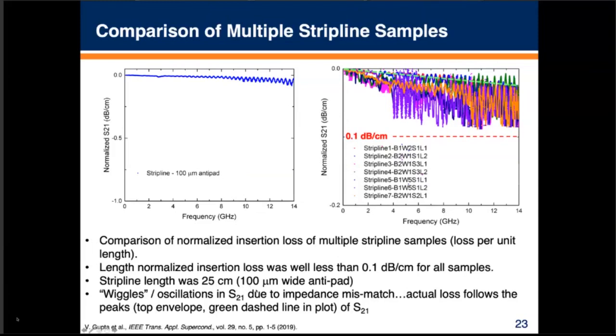And I mentioned here that we have a 100 micron wide anti-pad underneath that just to help with some impedance mismatch. And that's actually where these small wiggles come from. With such low loss, it doesn't take much of an impedance mismatch to cause these little oscillations. At each end of the line, you basically build up a bit of a resonator just because of that tiny, tiny mismatch combined with the tiny loss. And on the right here, we see sampling across multiple wafers and multiple samples. So there's a little bit of variation, but we're still down below that 0.1 dB per centimeter. And in the microwave world, that's just fantastic. I mean, it's hard to be super confident of your calibration down to that level of loss.